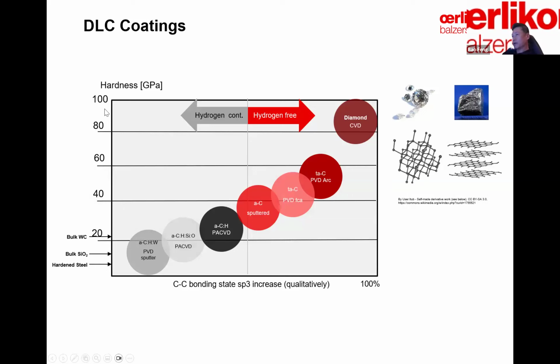On this chart, I also put hardened steel, about HRC 60 converted to gigapascal hardness, 6 or 7 gigapascal, and bulk silicon oxide, which can often be found in sand, and bulk tungsten carbide, which is often used as cutting tools to cut hardened steels. And we can see that diamond-like carbon coatings have a very broad range of mechanical properties, from the very top, close to diamond hardness, 100 GPa, to the other end of the spectrum, about 10 or so GPa, tungsten doped DLC.